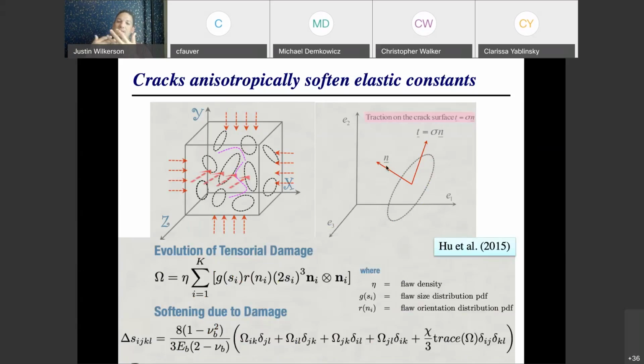And then they define an anisotropic tensorial damage tensor that basically sums up all of the crack volume associated with all of those cracks and then divides it by the volume of material. But it's a tensor because it accounts for the orientation of each of these crack families. So in here, n is the orientation vector for each family, S is the flaw size of the material, and eta is the flaw density in the material. When you carry out this operation and sum over all these parts, you get a damage tensor, and that damage tensor will create an anisotropic softening of the material. So this is an increase in the compliance of the material due to that anisotropic damage that's formed.